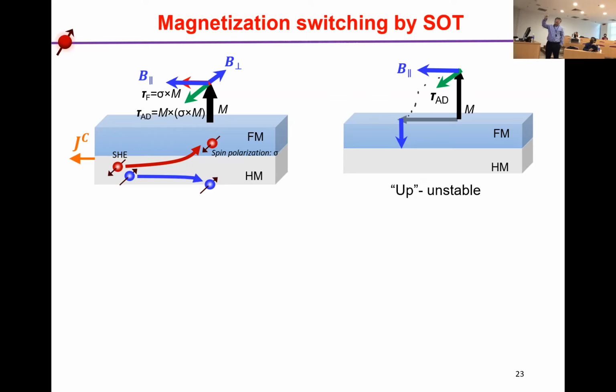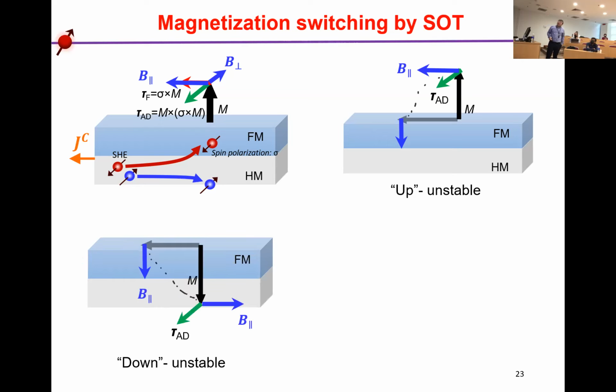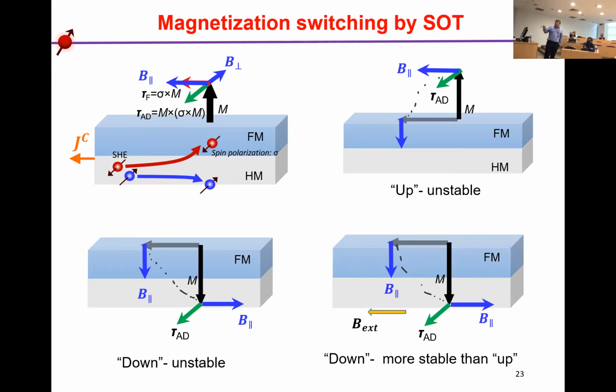So it will rotate the magnetization from up to down, and therefore the up direction is not stable. Then when the magnetization is down, the effective field still rotates the magnetization to up, so the down is also not stable. Then we can use an external magnetic field in the current direction to compensate this effective field. In this case, down is more stable than up. So by applying the current, we can deterministically switch the magnetization from up to down, because down is more stable.